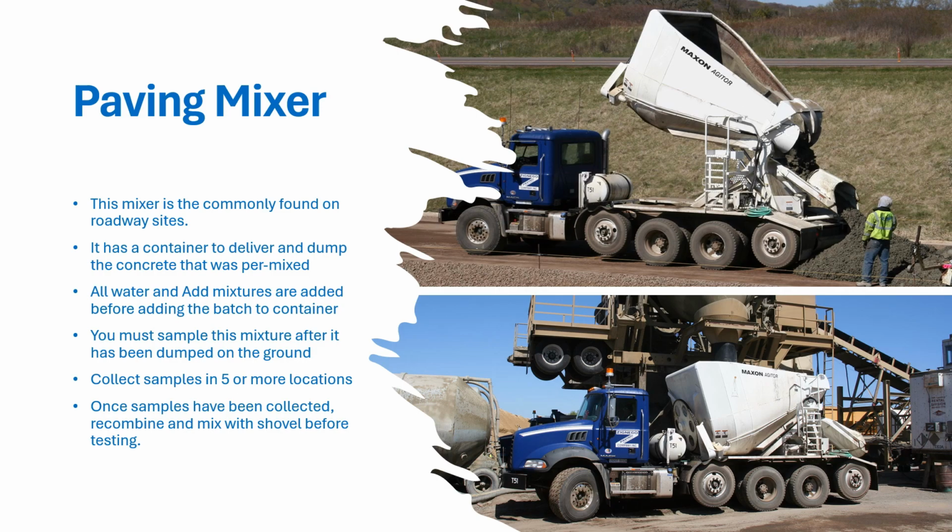You must sample the mixture after it has been dumped on the ground. Collect samples in 5 or more locations. Once samples have been collected, recombine and mix with a shovel before testing.